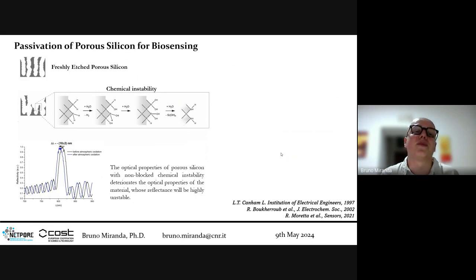But as I said before, porous silicon is very unstable. So the freshly etched porous silicon undergoes chemical instability that causes degradation of the material because of its oxidation. So the optical properties, for example, generally, if you leave the porous silicon as it is, undergo a blue shift instead of a red shift because you are losing material.